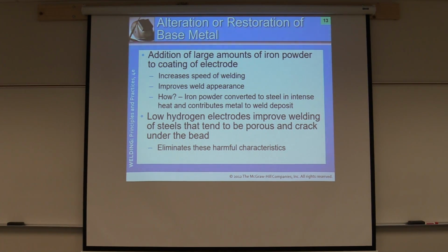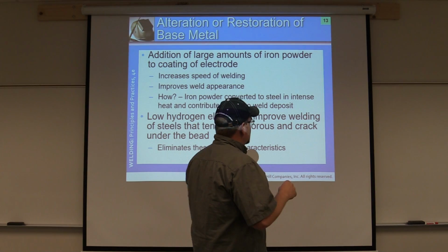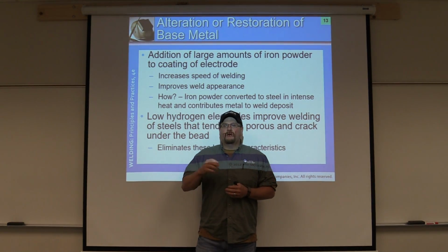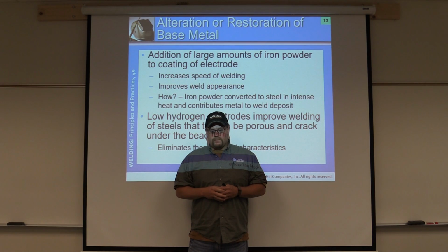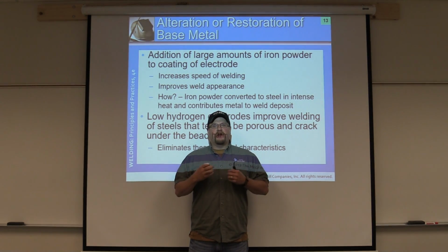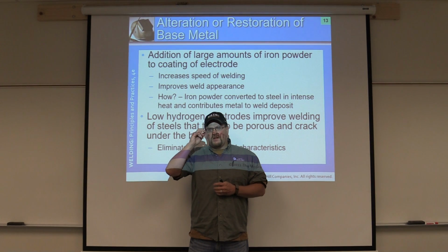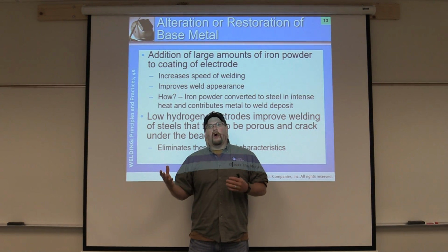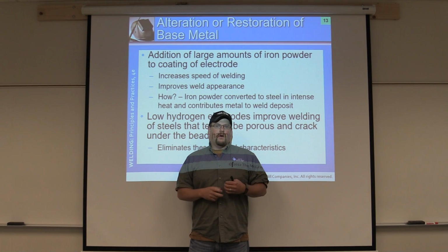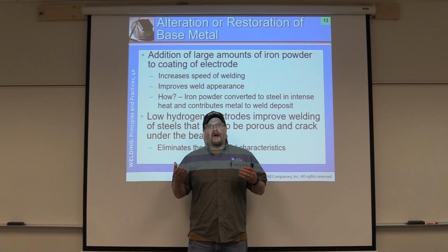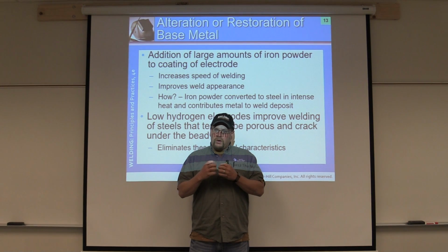All right, low hydrogen electrodes improve welding of steels that tend to be porous and crack under the bead. We'll get more into the underbead or hydrogen cracking. So what happens, let's talk about it for a minute. What happens here is low hydrogen rods are less susceptible to bringing hydrogen and moisture into the rod. 7018 specifically, if it's open to atmosphere, so you open the can or the box, whatever it was in, and it's open to atmospheric pressure, it's going to absorb that moisture. So it's pulling hydrogen in.